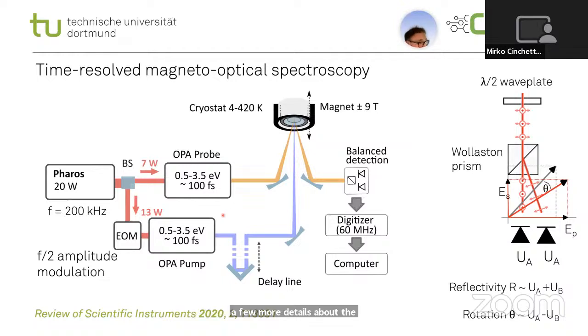Regarding the magneto-optical setup, I would like to mention that our sample is in a cryostat. In this cryostat, we can apply an out-of-plane magnetic field of up to 9 Tesla, which is very important if you study antiferromagnets. Then for the detection, we detect the reflected or the transmitted light from the sample, as you can see here. This is done using a balanced detector, which is connected to a high-frequency digitizer. With this scheme, we can measure the reflectivity, but also the rotation of the probe polarization.